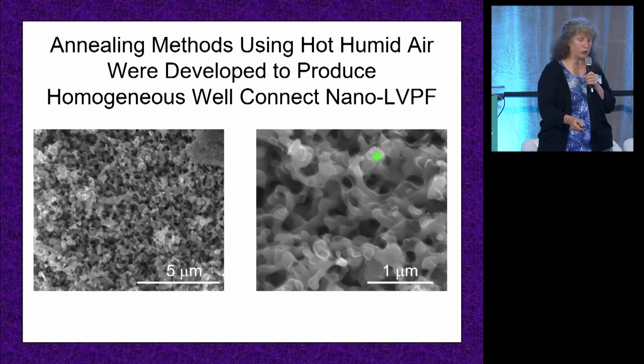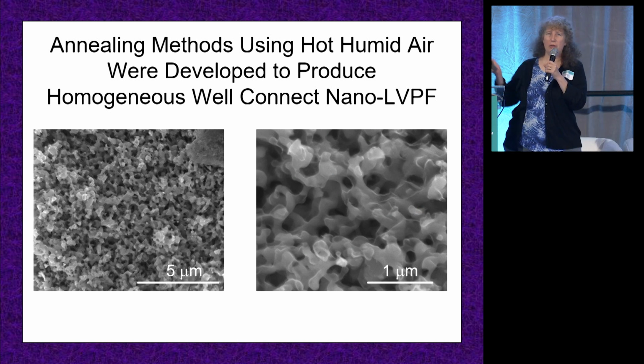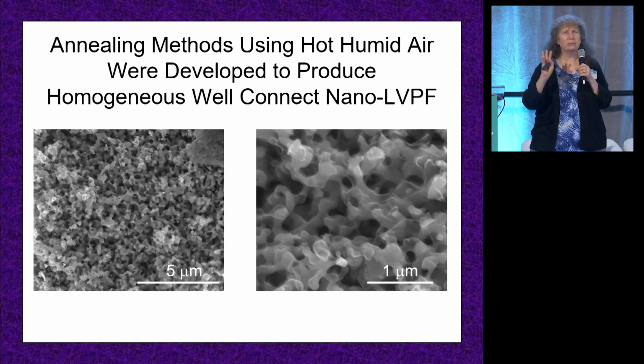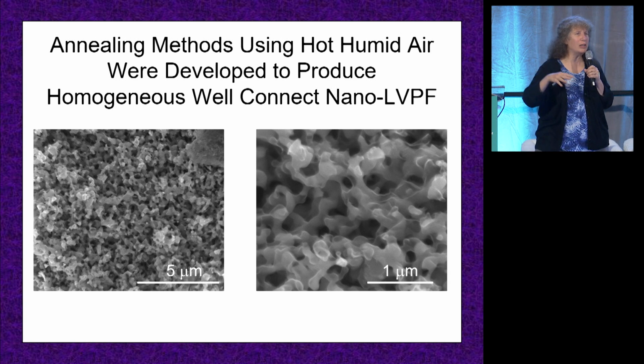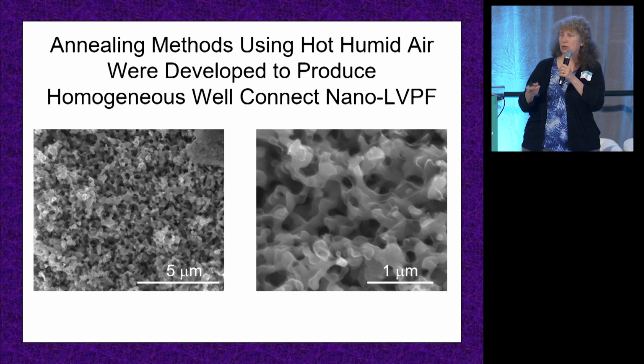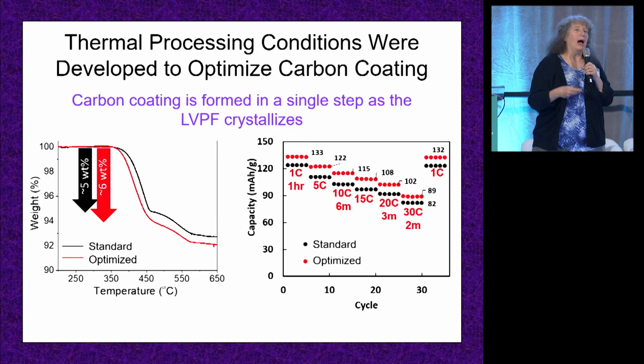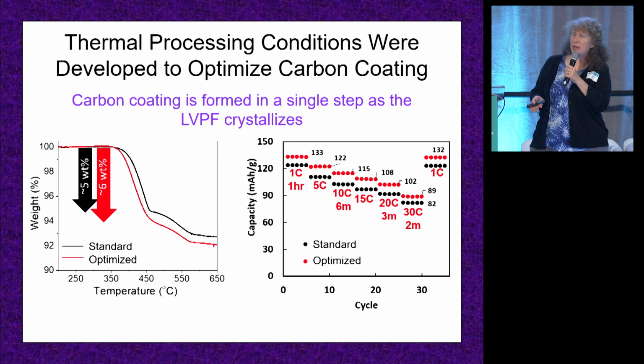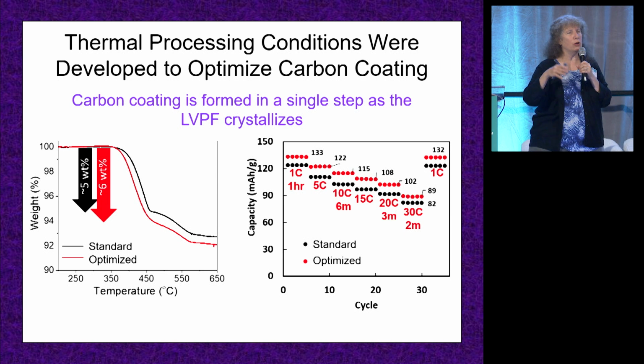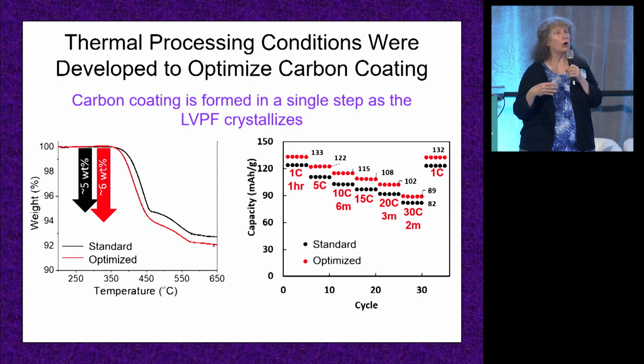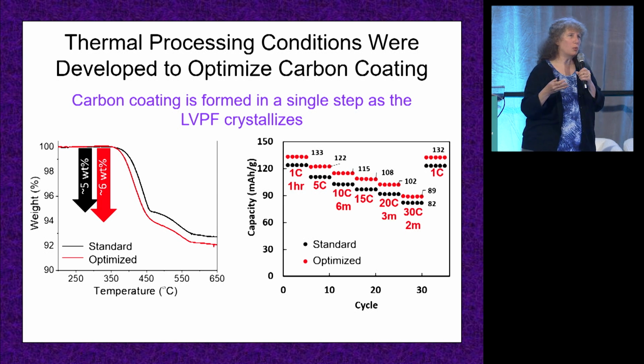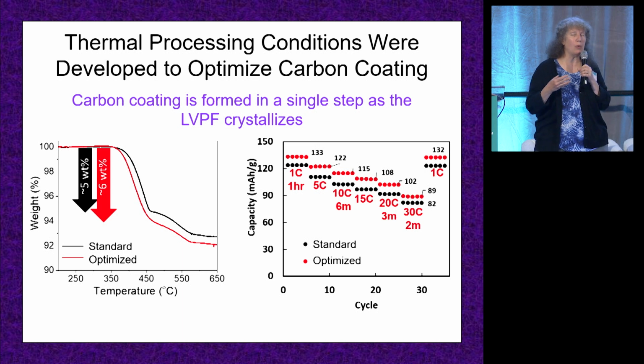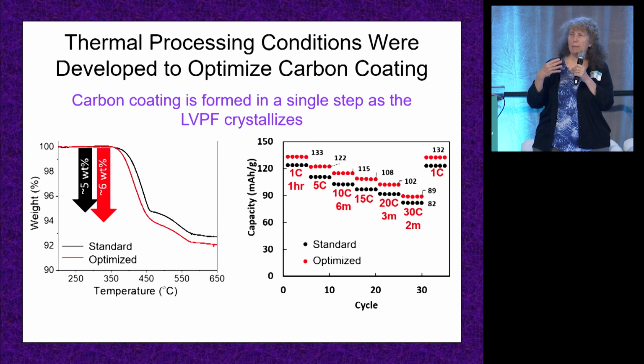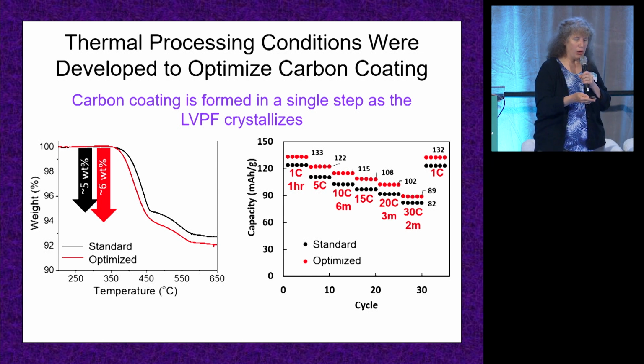And if you look at this picture, the key thing is the nanoscale network is completely interconnected. And so you can actually get electricity out and get lithium into all of the material. I said these materials are poor conductors, and as a result, you have to build in an integrative conductive carbon network around the material. And so the students also worked to develop methods to build that network. So the network is formed dynamically as you crystallize the material. You put in carbon precursors, and so they optimize the methods to maximize the amount.